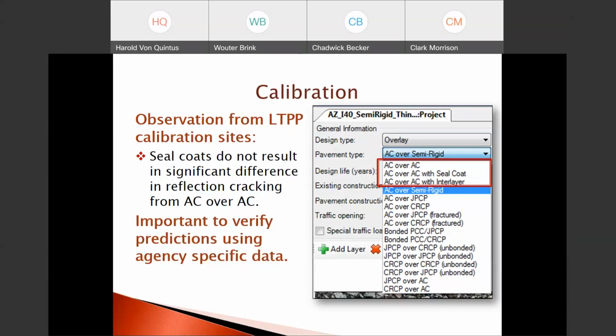The other reason is many of these non-structural layers, like seal coats, interlayers, and others, are highly specification dependent. And so in some cases, like in Arizona, where interlayers are used quite successfully, they would have a different set of calibration coefficients on using some of their rubber asphalt interlayers, as opposed to just a straight asphalt overlay. The factors would be different.